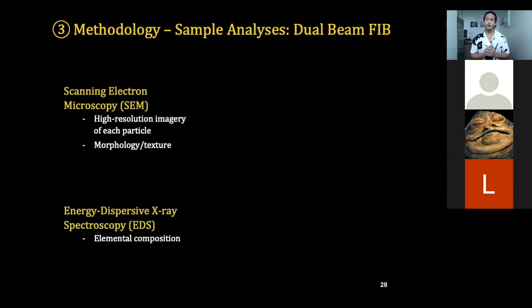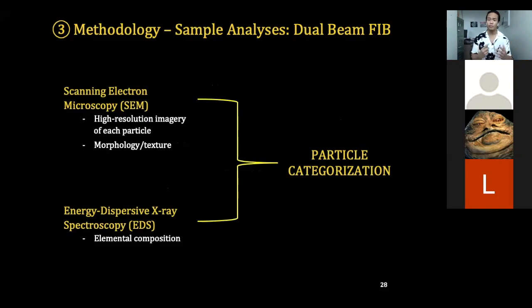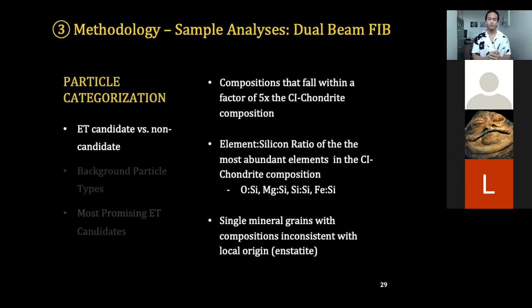So just circling back, the first two things we did using the FIB is SEM, which gives us imagery and information on morphology and texture, and then EDS, which gave us the elemental composition. These two things combined allow us to categorize the particles that we have in our samples. So now moving on to the particle categorization portion, we first divided our particles into two categories: extraterrestrial candidates versus non-candidates or background particles. So extraterrestrial candidates are particles that have compositions that fall within a factor of 5 times the CI chondrite composition, or essentially the composition of the sun.